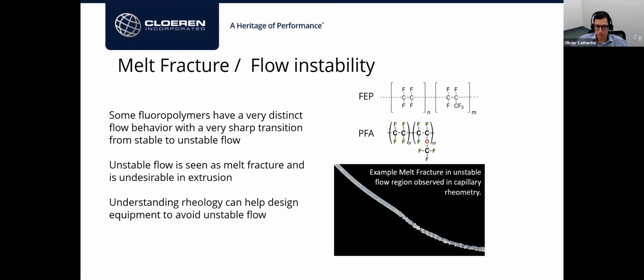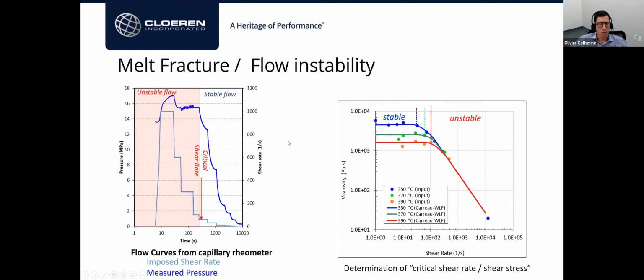So it's nice to observe that, but actually being able to measure this phenomenon is also quite good. So here's an example of pressure measurements from the capillary rheometer for a fluoropolymer, and this is over time. So we impose different shear rates. We schedule those shear rates through the software of the rheometer, and as a result, we are measuring the pressures. And as you can see, in this experiment we start from high shear rate to low shear rate, right? And you can see that at the very beginning, we developed a very unstable flow. We have a lot of pressure fluctuation. And eventually, pressure stabilizes in a steady region there, and we are able to collect an actual pressure value.